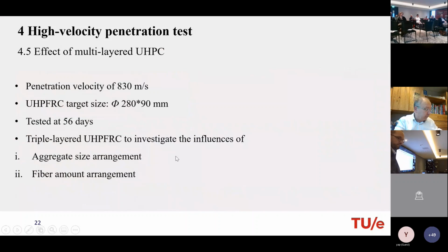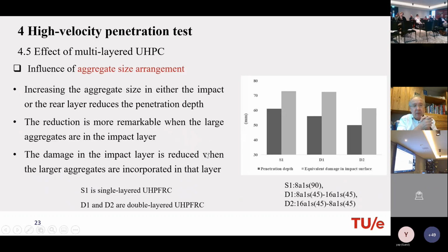Well, here a little bit of information about the multi-layer research that we did. We looked at 830 meters per second. Here you can see the target size. And we had double and triple layered UHPFRC, to study the aggregate size and the fiber amount. Well, we use a single layered concrete.